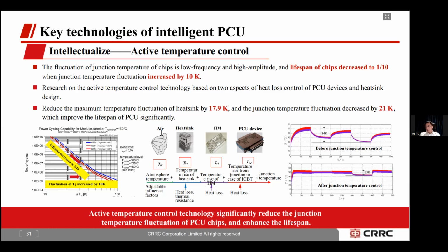Then we researched on the active temperature control technology based on two aspects of heat loss control of PCU devices and heat sink design. In the end, we reduced the maximum temperature fluctuation of heat sink by about 18 K and decreased the junction temperature fluctuation by 21 K, which could improve the lifespan of PCU significantly. Active temperature control technology significantly reduced the junction temperature fluctuation of PCU chips and enhanced the lifespan.